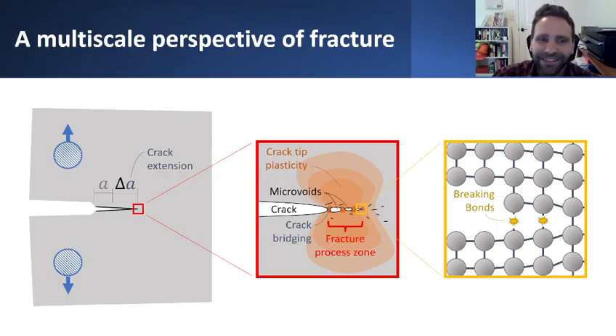Now, that's a fairly coarse-grained view of what's really going on. If we go to that microscale perspective, what's happening in the material, it's worth mentioning that what we'll see will depend very strongly on the type of material that we're looking at. But if we're looking at fracture happening in some kind of metal, for example, like steel, what you might see is something that looks like this. A much more complicated picture of multiple, cascading mechanisms contributing to fracture growth and development. So a few things that I'll point out here include the fact that indeed there is still the crack that we had previously, and it's advanced by some distance, delta A, so we're really looking at the crack tip in this extended zone of fracture now.